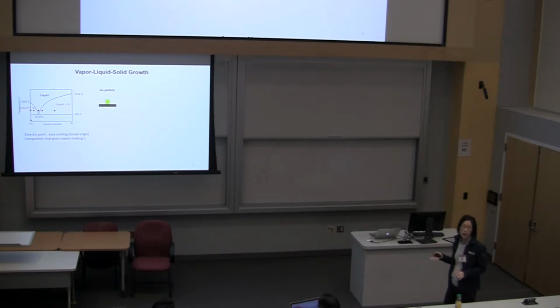I'm going to use silicon nanowires as an example. It's a classic VLS case. We're going to use a gold nanoparticle as a nucleation center, as a growth catalyst. Okay? So let's look at the gold silicon binary phase diagram. Here's a eutectic point. If you have about 18.6% silicon, then this gold silicon alloy will melt at 363 degrees Celsius, the deep eutectic point, okay?